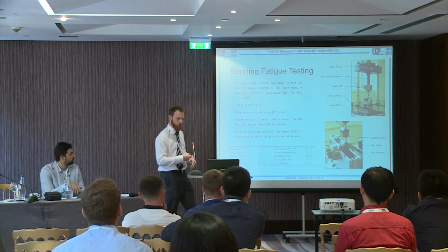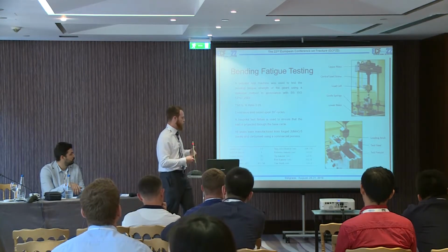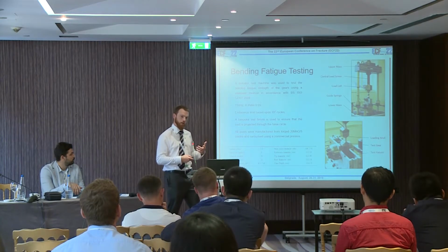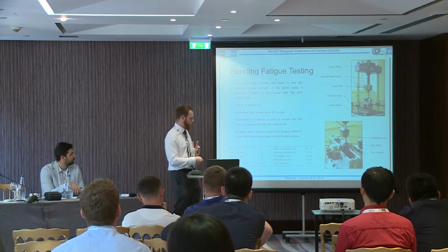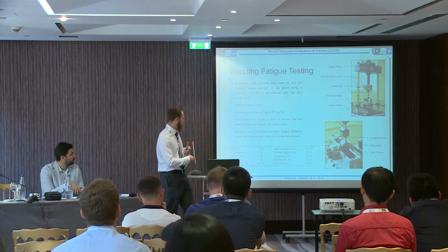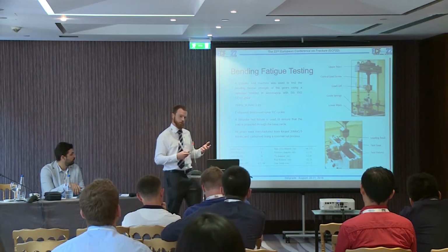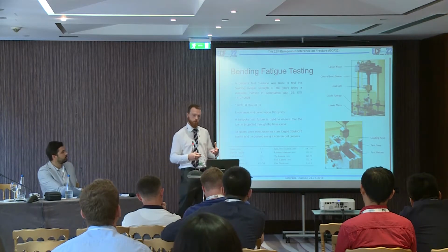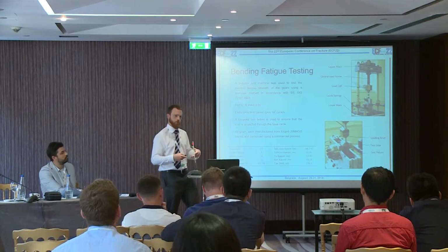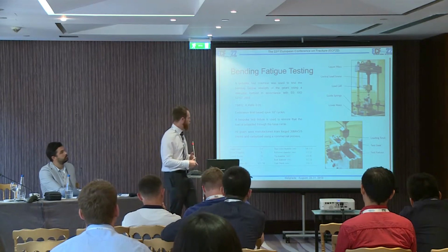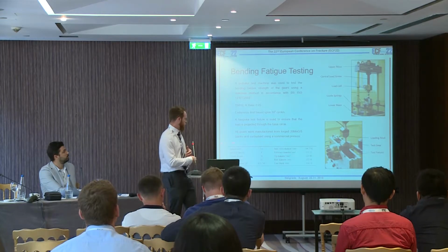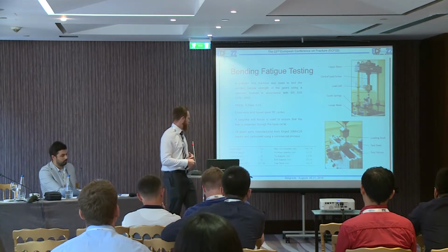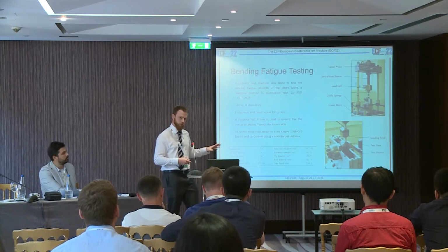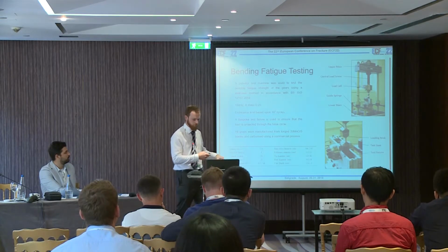We use an R ratio of 0.05, and the gears themselves were manufactured from a forged case carburizing steel, typical of the automotive industry, so you can see that here. Forged blanks and then manufactured using a standard process, and again that's making sure that what we're doing is typical of the actual application that these gears come from. So there's some gear data at the bottom there if anyone's interested in recreating these, and these were gas carburized using a commercial process.